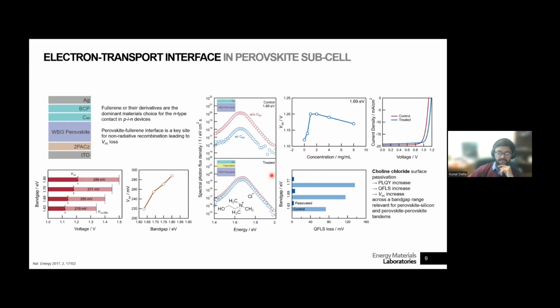And when you look at this passivation across 3 different band gaps, so this is the quasi-Fermi level splitting loss calculated from this absolute photoluminescence spectrum. And the moment you passivate it, it drops significantly. And then this quasi-Fermi level splitting loss keeps on rising, as I showed here. But the passivation keeps this loss to like 4 to 7 millivolts. That's quite spectacular, I think. And that eventually, if you put it in a device, results in an increase in the VOC that you can see here. And that basically means that overall your device performance goes up, right? So now we have looked at this 2PACz interface and the C60 interface as well, and kind of optimized it to improve the VOC of these devices.